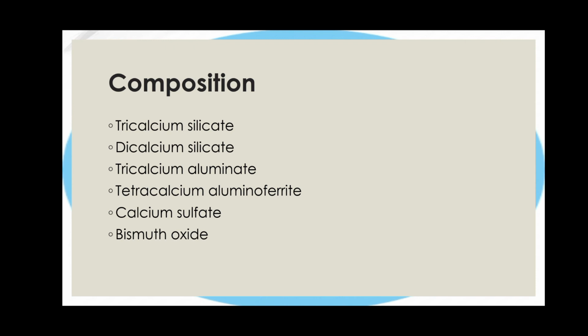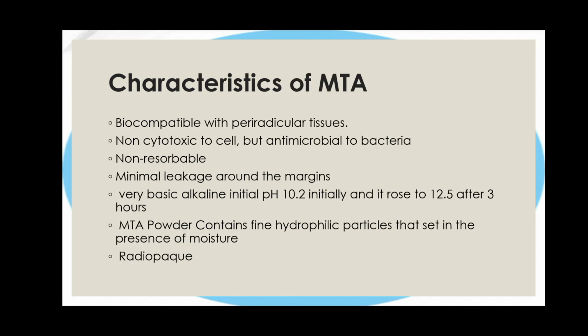Composition: tricalcium silicate, dicalcium silicate, tricalcium aluminate, tetracalcium aluminoferrite, calcium sulfate and bismuth oxide. Characteristics of MTA: biocompatible with periradicular tissues, non-cytotoxic to cells but antimicrobial to bacteria, non-resorbable, minimal leakage around the margin, very basic alkaline, initial pH 10.2 and it rises to 12.5 after 3 hours. MTA powder contains fine hydrophilic particles that set in the presence of moisture, radiopaque.